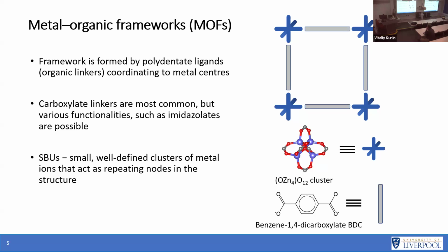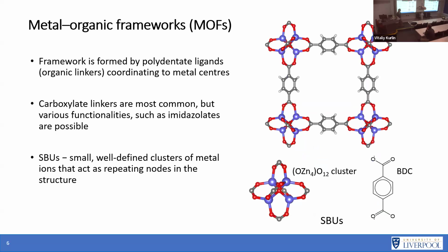So you also have these SBUs. These are little well-defined clusters of metal ions, and these are the repeating nodes in the structure. Essentially, you could represent it like this. This is a simplistic diagram of our MOF here with our metal nodes connected by organic bridging linkers. Obviously, it's more likely to look like this in real life, where you've got these clusters. In this case, you've got a zinc cluster coordinated by these BDC linkers like so.